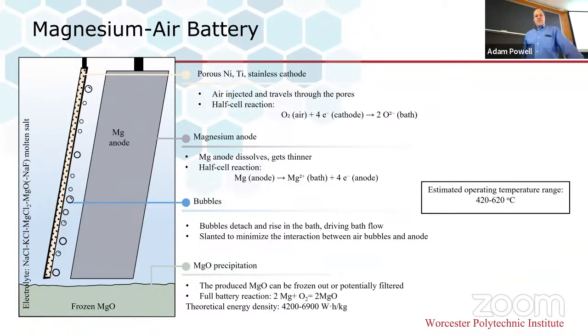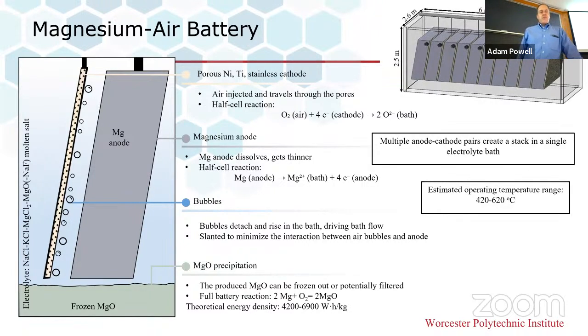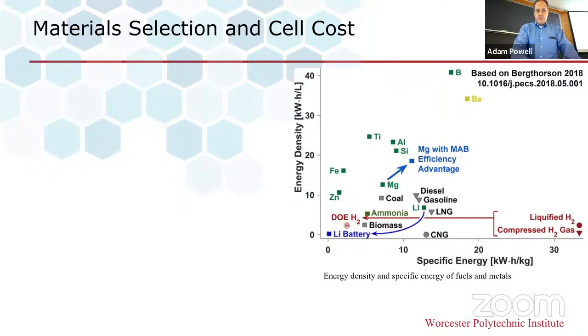The operating temperature of this molten salt electrolyte is pretty high, though, and that limits us. So we can't scale it down because you would lose too much heat through the sides. So we think the minimum size is about a shipping container. This is a schematic in a 20-foot shipping container with a series of 10 anode cathode pairs in series in order to generate more voltage, which has various advantages.